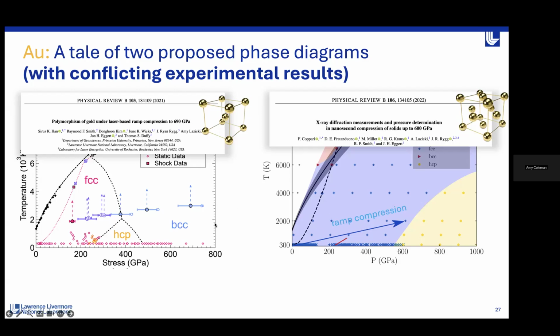On the left-hand side here, I'm showing a paper that was published in PRB in 2021. The results from this paper show something that's more supportive of the alternative phase diagram, whereby just below 400 GPa, there is in fact a transition from this purple FCC phase to this blue BCC phase. So we've really got two things that are published and contradicting each other.